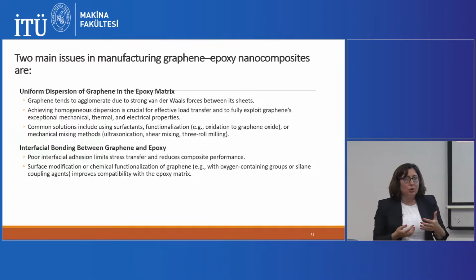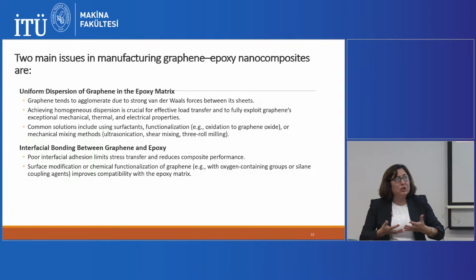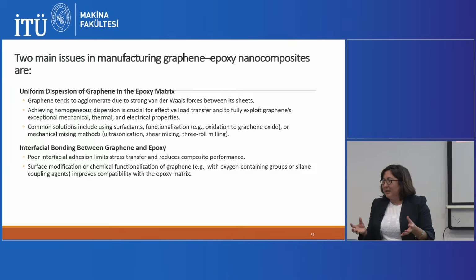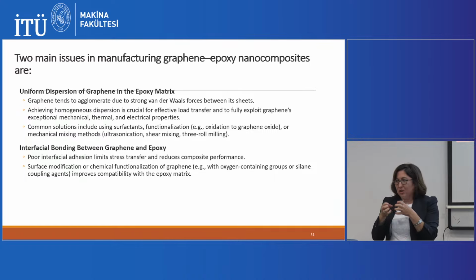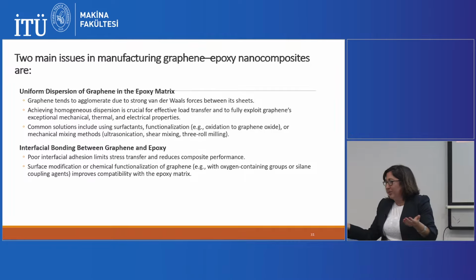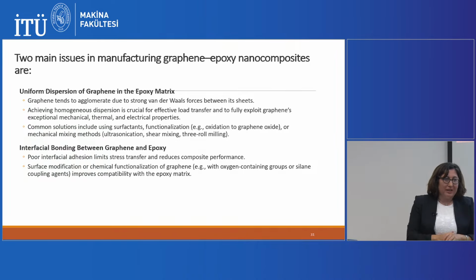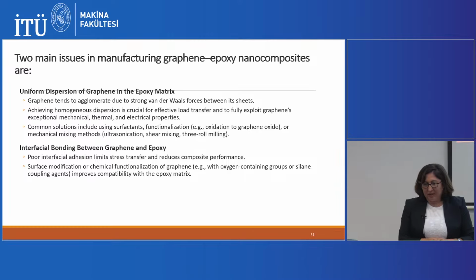The second issue, you have to disperse, yaymak. You have to disperse the graphene evenly, homogeneously in the matrix. If you cannot disperse the graphene, they agglomerate. Agglomeration is topaklanma. So initially you start with graphene, but at the end you get maybe graphite. So there is no use of so much information about the graphene. That's why this uniform distribution is also important.